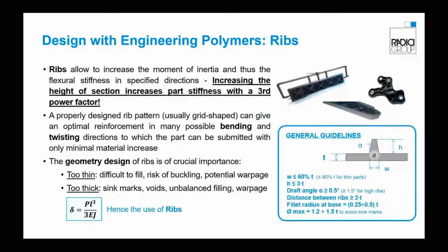Ribs are used in order to increase the moment of inertia and thus the flexural stiffness in a specified direction. It's very interesting that increasing the height of the section increases part stiffness with a third power factor. A properly designed rib pattern, as we can see from the pictures on the right, gives an optimal reinforcement in many possible bending and twisting directions, to which the part can be submitted, with only a minimal material increase.